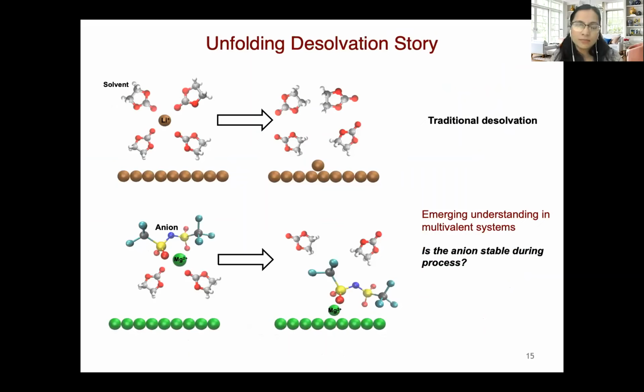Okay, and this work basically improved our understanding of what's happening in magnesium ion batteries and how it's different than lithium ion batteries. In lithium ion batteries, if you want to deliver this lithium to the surface, you need to just strip away these solvent molecules. But in magnesium ion batteries, due to high tendency of this ion pair formation, it's actually the anion which delivers magnesium to the surface during the charge transfer process. And with this understanding, it became important for us to study if the anion remains stable during this process or not.